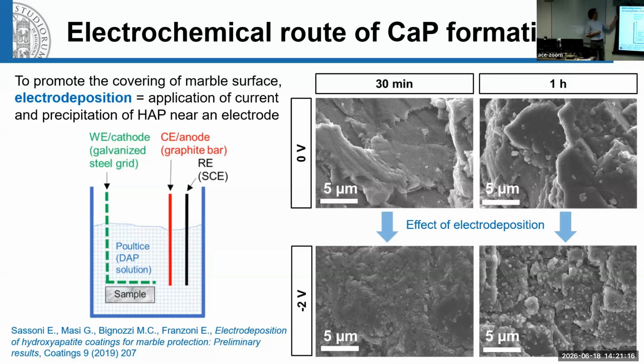So taking inspiration from this, we tried one of the techniques that are used in the biomedical field to deposit hydroxyapatite over metal. Electrodeposition means that by providing an electric field, it's possible to accelerate the formation of these coatings. And indeed, if we watch here what was formed over marble for the same time without electrodeposition and with electrodeposition performed in certain conditions, as you can see, it's possible to accelerate the process of formation of these coatings to obtain a more continuous coating in a shorter time.